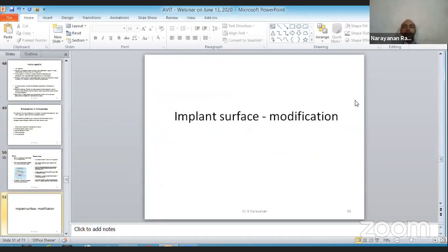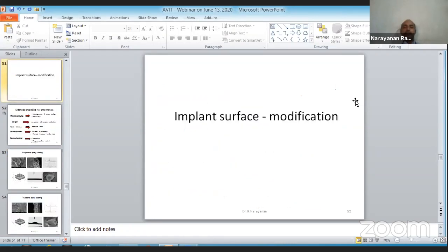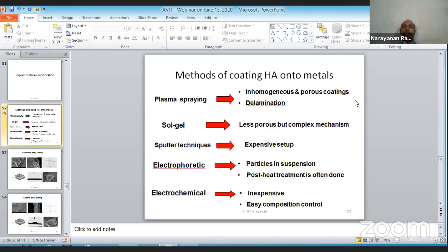There are different techniques of coating. Let us say that you want to improve the chemical state and you want to deposit hydroxyapatite onto metals. It can be a stainless steel metal, or it can be cobalt, or it can be titanium. On these implants of your choice, you are trying to promote a coating of hydroxyapatite. Now with this, there are many methods. I use this technique for my studies, but plasma spraying is also used.